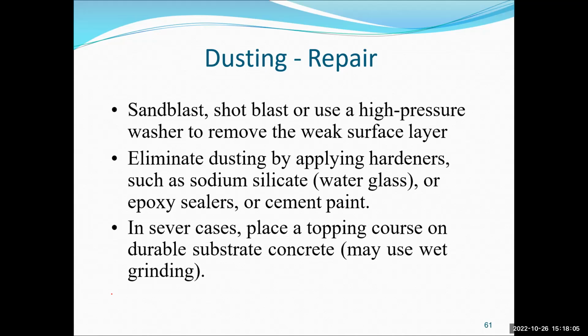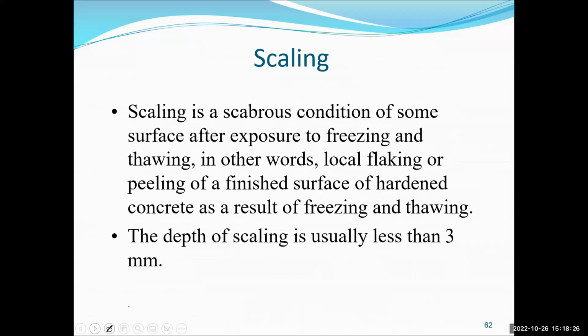Right, thank you, Jared. So the way to repair the dusting, because the top surface would be loose, is to remove the loose materials and use some kind of epoxy material that binds all these materials together. And in severe cases, you put an additional layer on the concrete.